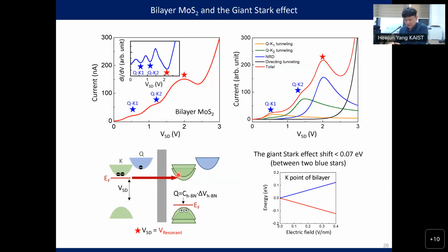So if we estimate physically the energy difference between the two bands by the giant Stark effect, it's less than 70 milli eV. And this is room temperature data. Room temperature means we have thermal energy fluctuation of 25 milli electron volt. So this tiny energy difference between two bands could be measured with a large source drain voltage bias and then the shoulder feature. So this is one advantage of this momentum-driven resonant tunneling. This is called the giant Stark effect because in the hydrogen atom, the energy split is on the order of milli-eV. Here we have tens of milli-eV, so more than 10 times larger.